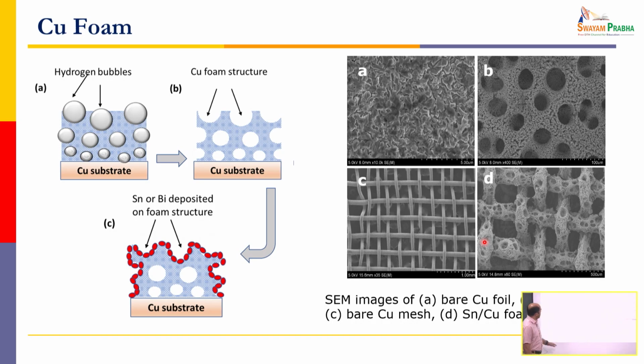So we started with, as I said, a copper substrate. We apply a current to make it into a foam. This process is called the hydrogen bubble template method, where in aqueous solution, when you pass high current, hydrogen bubbles will form. Hydrogen from water will come, and those bubbles will create a space which will make it a foam. Okay, so this is a mesh you can see, or this is a foil. When we make this, this is a foam.